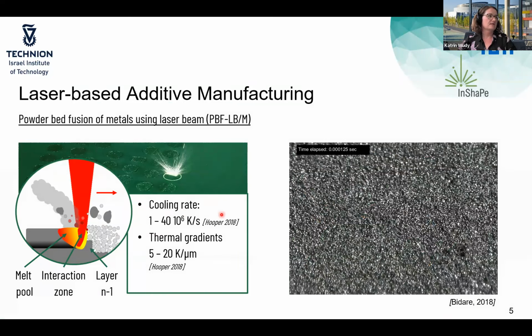Now, what is the challenge during processing? The challenge is that we have really high cooling rates. For metal materials, this means always that the cooling rates determine the microstructure formation at the end. And if we have a look in space, we also have high thermal gradients. And if we now have a look in detail at this process where the laser interacts with the powder bed, you see a highly dynamic process. So this is actually the laser beam, the bright spot here. And what you can see is this highly dynamic process. We have a lot of powder particles flying around, and these powder particles also sometimes interact with the laser beam and with other powder particles, and then you get some kind of agglomerates of the powder particles, and these would be, for example, scrap material later on. Or sometimes it happens that these powder particles flying around land in the before melting area, which is this one, and create defects in our components later on.